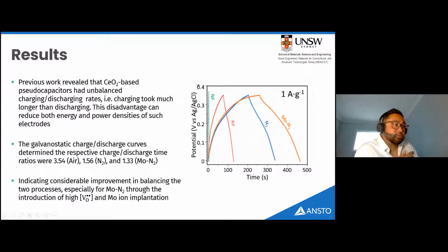So this slide shows the results of chronoamperometric measurements done on the samples. Previous work by UNSW on cerium-based oxide pseudocapacitors showed that they suffered from an unbalanced charging-discharging rate, in that the charging took much longer than discharging, which can reduce both the energy and power densities. But in this work, the curves determined that the respective charge-discharge time ratios were 3.54 for the air annealed, 1.56 for the nitrogen annealed, and 1.33 for the molybdenum implanted nitrogen annealed sample. So it indicated considerable improvement in balancing the two processes, that charge-discharge, especially for the implanted sample, likely as a result of the introduction of both high oxygen vacancy concentration as well as the molybdenum donor defects.